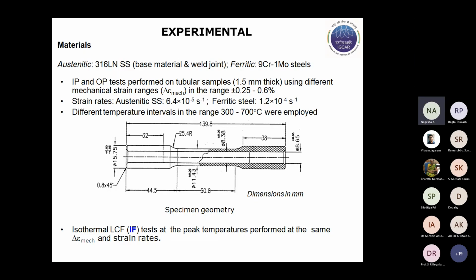So I will just give some important results which we have obtained on austenitic stainless steel, base metal and weld joints, and ferritic 9 chrome varieties of steels. We have investigated 9 chrome moly steel and reduced activation ferritic martensitic steel, which are respectively used or potential materials. 9 chrome moly steel is the material for the steam generator components of fast reactor, whereas there is another type of similar steel which I'll be coming to a little while later.